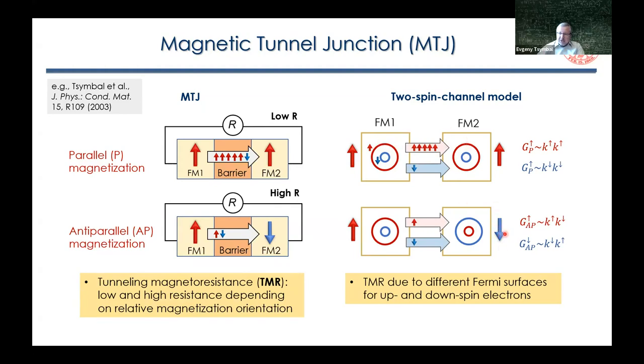If you now switch the magnetization orientation, we have a mismatch between the Fermi surfaces because the spin is reversed in the right electrode. And this mismatch may be considered as a substantial enhancement of resistance for anti-parallel magnetization. So I'm using this concept because that will be relevant to what I'm going to discuss next.